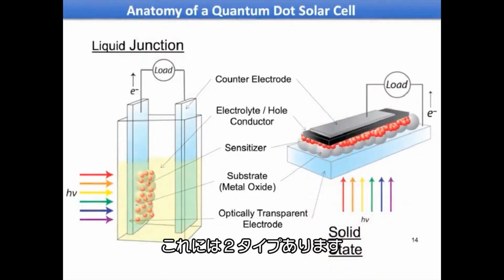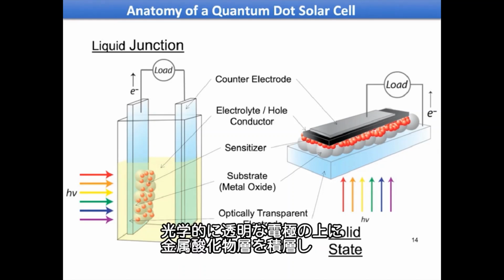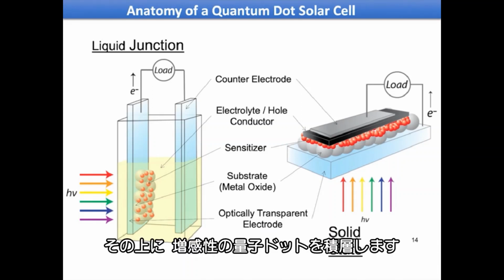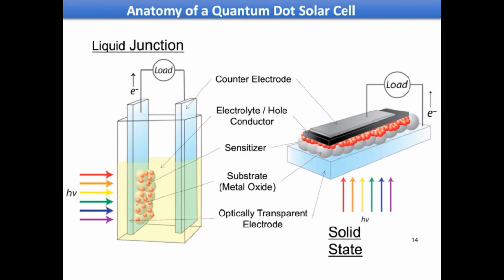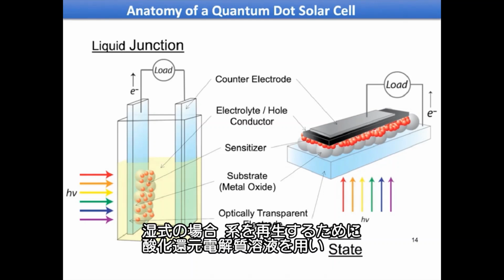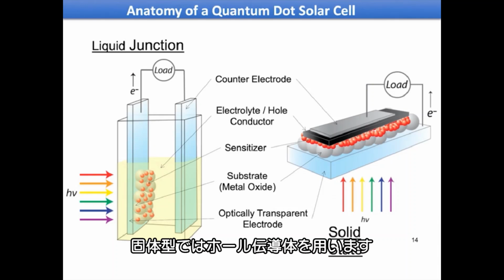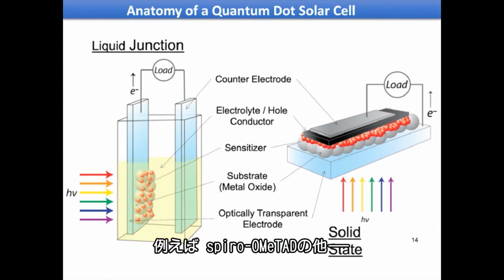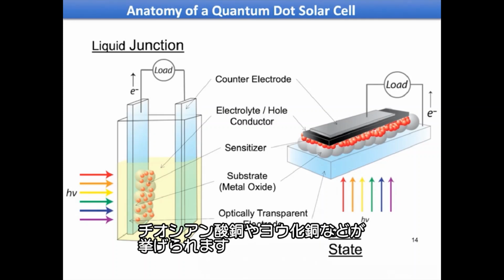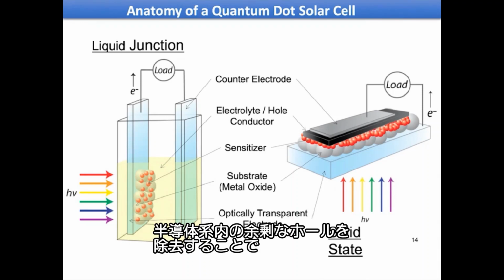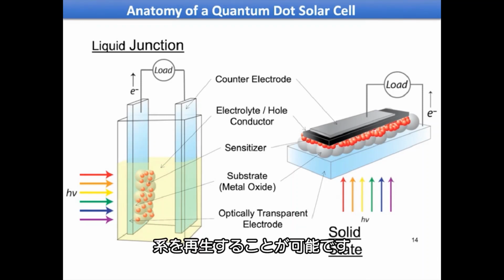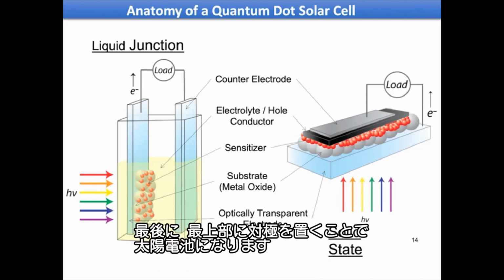There are two types of quantum dot solar cells. One is liquid junction, another one is solid state solar cells. Both operate on the same principle. As you can see here, it consists of an optically transparent electrode on which you put a metal oxide substrate, on which you put sensitizing quantum dots. In the liquid junction we use a redox electrolyte to regenerate the system, whereas in the solid state we use a hole conductor, so it could be spiro-OMeTAD or an inorganic hole conductor like copper thiocyanate or copper iodide, which helps to regenerate by scavenging the excess holes in the semiconductor system. And finally on the top you have a counter electrode to assemble this solar cell.